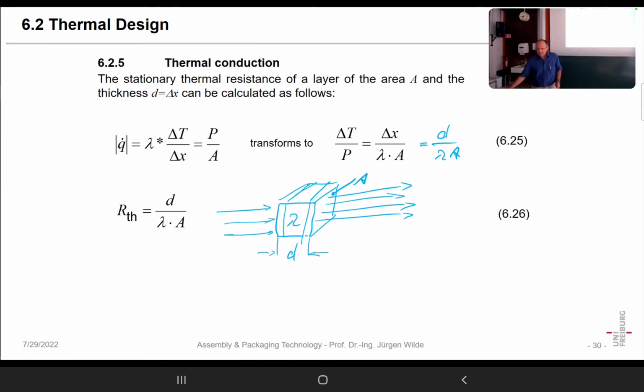And that means to come to a large area, when we have a point source, we also need to have a large distance. And that's the reason why concentrated heat sources are always making problems, because you first have to distribute the heat until you can spread it efficiently. And to that purpose, for such point-wise sources or sources in small volumes, you also need materials with a high heat conductivity. And fortunately, silicon is quite good at conducting heat. Also, silicon carbide is very good. Diamond is much better, so that's one of the reasons why engineers are working on developing power semiconductors on diamond.